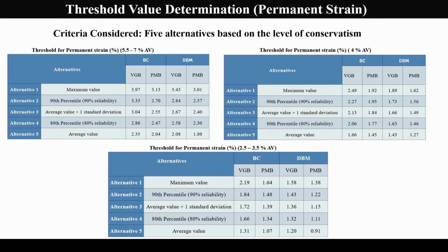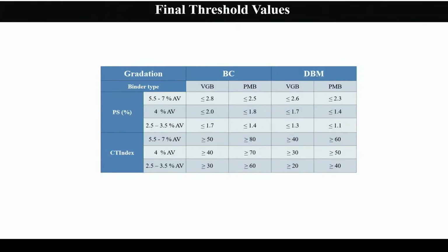So for the different approaches we tried to calculate, and based on the lab study, for the rutting we have thought to proceed with 80% reliability, because the pavement initially will be subjected to primary and secondary compaction. However, for the CT index, we try to keep the criteria a little stringent, because it will occur after a few years of life. So we proceeded with the average value. However, we have made a field test section near Ayodhya, Jagdishpur, and we will be verifying this value so that our initial threshold specification will be modified on the basis of the field validation.